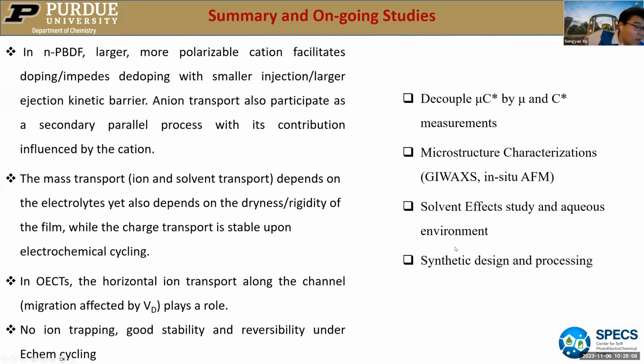So this is the categorization I have done so far. Generally, in n-PBDF material, the larger, more polarizable cation facilitates doping but impedes de-doping, with smaller injection but larger ejection kinetic barrier. The anion transport plays as a secondary parallel process, where its contribution depends on the interplay of the cation and anion. And the mass transport studied by EQCM includes both ion and solvent transport, depending on the electrolyte but also on the rigidity or dryness of the film.